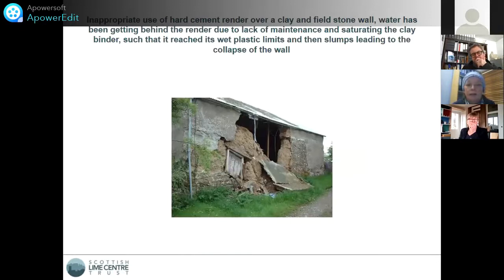And this is probably a bit of an extreme case, and it's from a building in Devon, and it's made up of field boulders bound in a clay or earth mortar, and then some bright spark thought it'd be a good idea to cement render it and then not maintain it, and over time the clay binder has been saturated such that it reached its wet plastic limits and then has slumped, leading to the collapse of the wall, and something only fails once.